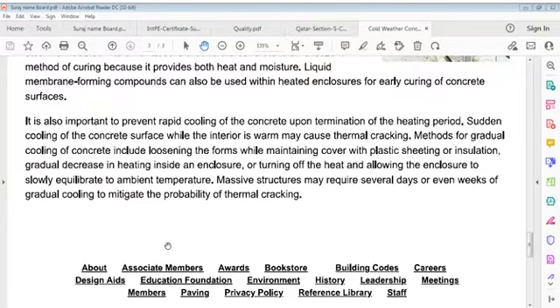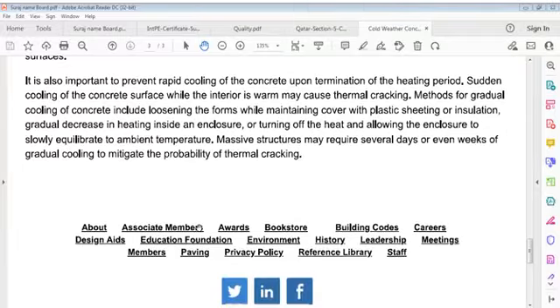Massive structures may require several days or even weeks of gradual cooling to mitigate probability of thermal cracking. It's also important to prevent rapid cooling of concrete upon termination of heating period. Sudden cooling of concrete surface while interior is warm may cause thermal cracking. Methods for gradual cooling include loosening of forms while maintaining cover with plastic sheeting or insulation, gradual decrease in heating inside enclosure, or turning off heat and allowing enclosure to slowly equilibrate to ambient temperature. Massive structures may require several days or even weeks of gradual cooling.